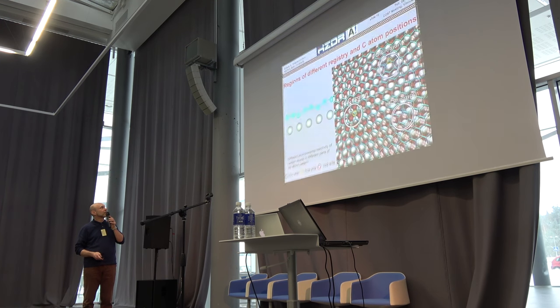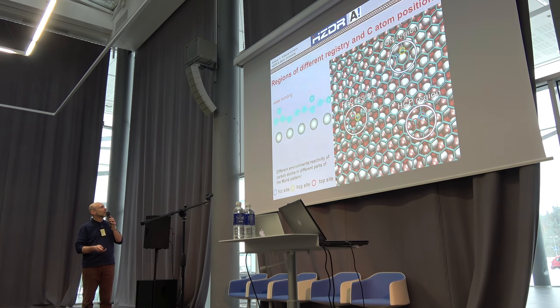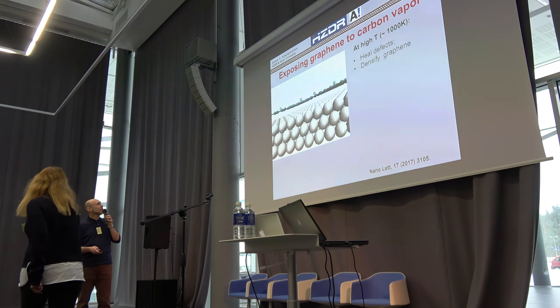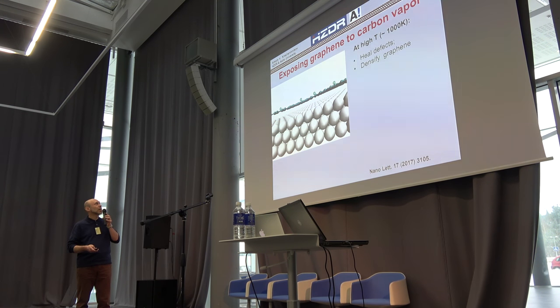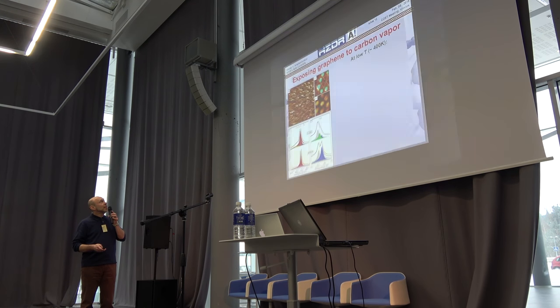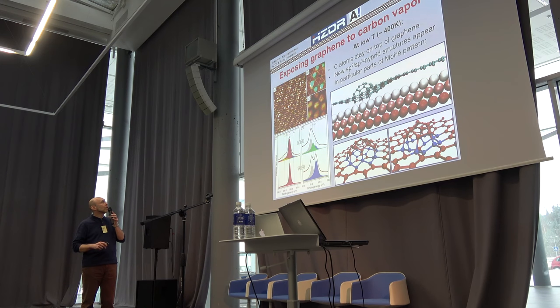This also means that if you deposit extra carbon on top, in some areas the interaction will be pretty weak and non-bonding, while in other areas it can be pretty strong because the material is partly already in SP3 hybridization — it may actually go down and become more hybridized. Experimentally, this is what Thomas observed. At high temperatures, you see results that are to some extent expected — you get graphitization. What's interesting is that carbon goes through, and our calculations indicate you can get a second layer at high temperatures. But the interesting thing is what happens at about 400 Kelvins.